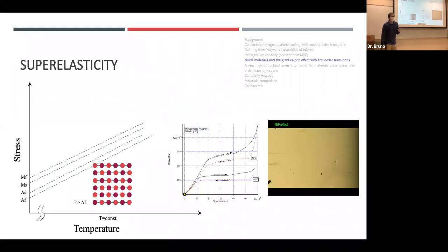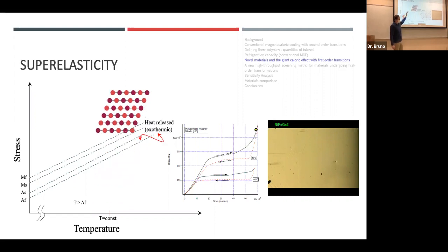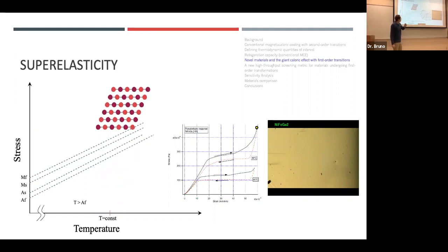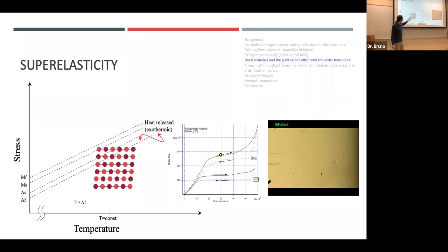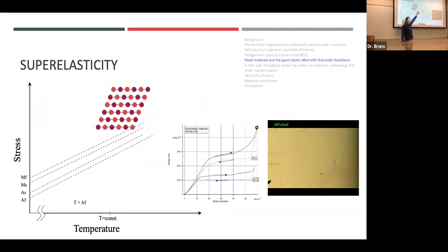These materials also exhibit something called superelasticity. In order for superelasticity to work, you need to be in the high temperature austenite phase, where you have a cubic crystal structure. You can load it with mechanical stress. You get a linear elastic response of austenite, and you'll reach a critical stress where it will trip it. You'll force it into the martensite phase. And I want to just point out, when you force it into the martensite phase, you get a latent heat of transformation because you have a different crystal structure. It's just like latent heat of vaporization in your thermodynamic cycle at home, right, with your refrigerator, your air conditioning unit.